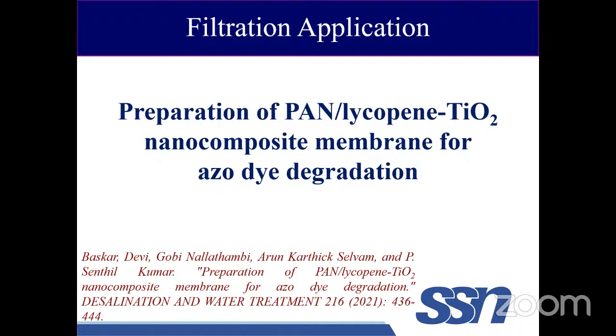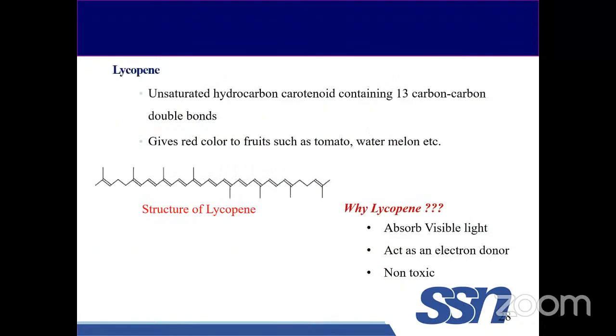To give you an idea, lycopene is an unsaturated hydrocarbon containing 13 carbon-carbon double bonds, which is the reason for the red color in the fruit tomato and watermelon, right? So why we choose lycopene is because it absorbs visible light. As we are doping lycopene with TiO2, it is going to activate TiO2 as a visible light photocatalyst, so that the problem can be overcome. And it acts as an electron donor, which again helps in the photocatalytic degradation process. And this lycopene is going to be extracted from natural sources like tomato and watermelon. It is a non-toxic material.